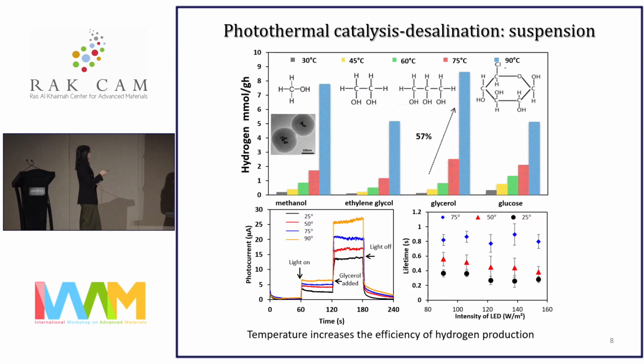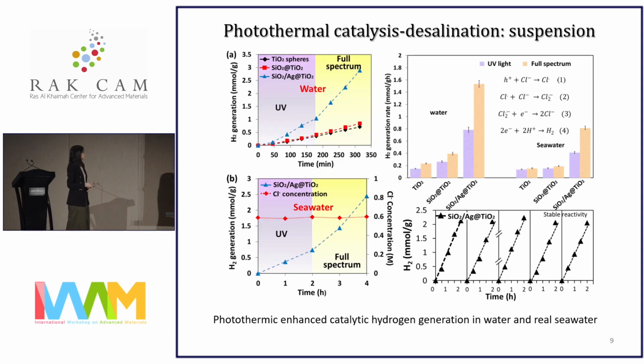So here shows the hydrogen plot at different temperatures with 4 different sacrificial agents. It's quite apparent that the temperature elevation increases the efficiency of hydrogen production. And among them, the glycerol shows the highest improvement, about 57%, when temperature increases from 30 to 90 degrees Celsius. And it is postulated that it's due to the increased hole scavenging activities of the sacrificial agent. And this in turn correlates with the improved or prolonged lifetime of the photo-generated carriers.